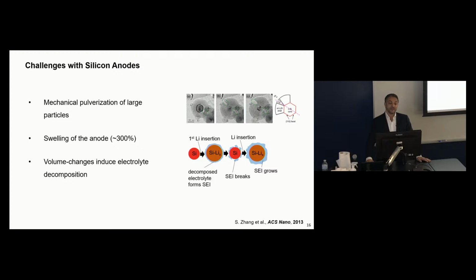And when you have lithium-ion batteries, the anode is at such a low electrochemical potential that all electrolytes that are currently being used become electrochemically reduced; they decompose. So when the volume changes in the material are small, this decomposition product may form a very stable solid electrolyte interface, or SEI layer, that prevents further electrolyte decomposition. However, if you have such dramatic volume changes, it's very difficult to stabilize the SEI.